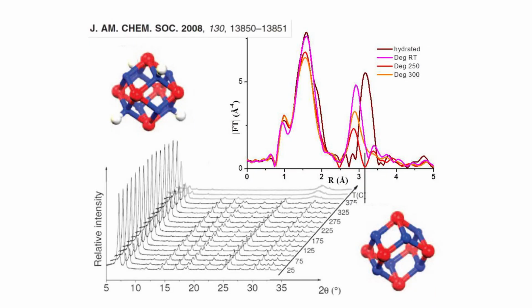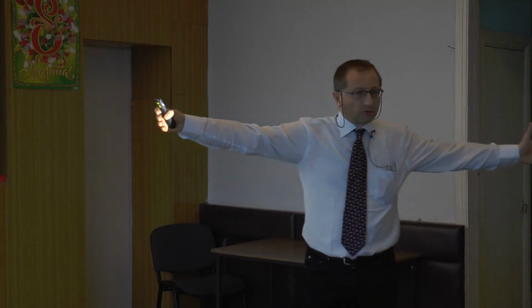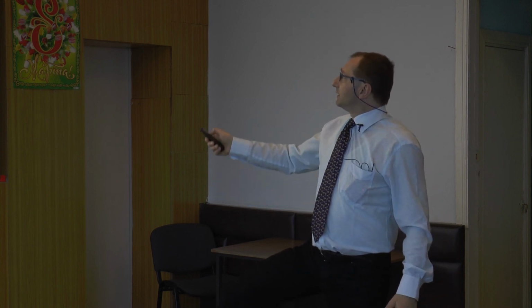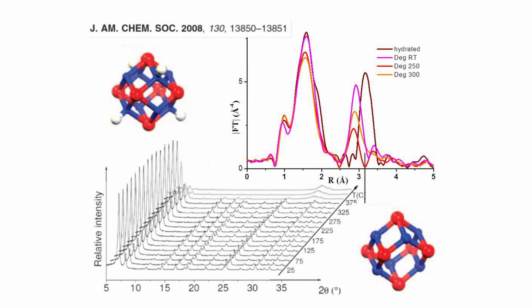Okay, so we can follow the solvent removal reaction with EXAFS. So this is the inorganic cornerstone. Of course, if we do EXAFS, we have a local picture around only the metal atoms, while with diffraction we have information on the whole structure. And what we see is that this is the first shell, zirconium-oxygen distances. And this is the second shell, zirconium-zirconium. And this is the third shell, zirconium-zirconium, on the diagonal of this. This is a perfect octahedron. So imagine an octahedron with 4 zirconium in square planar plus 2 zirconium like this, connected with oxygen as depicted in this picture here.